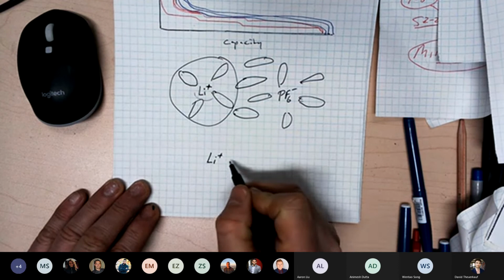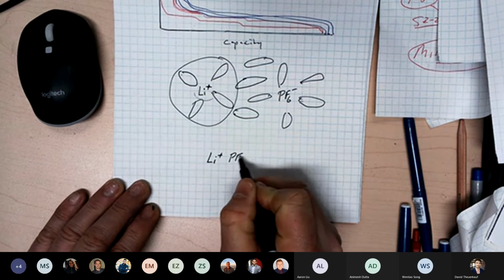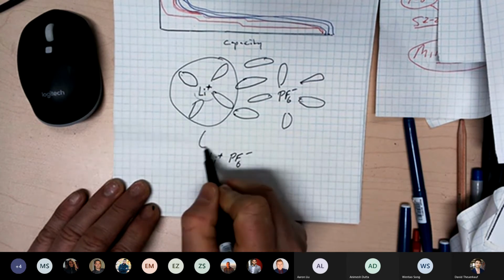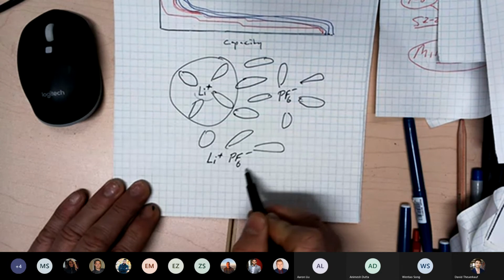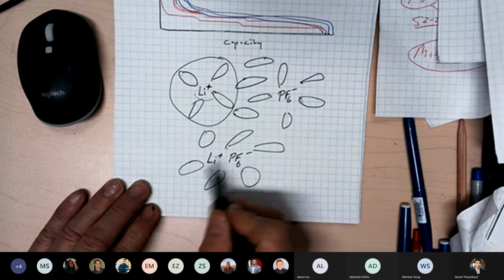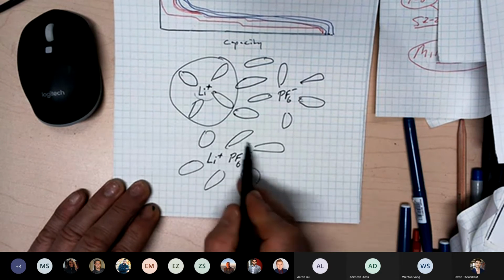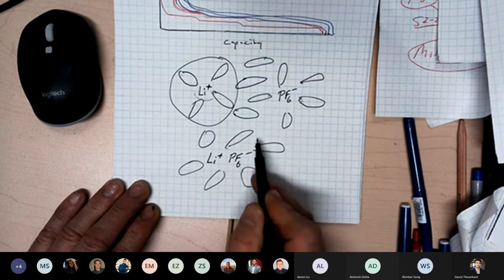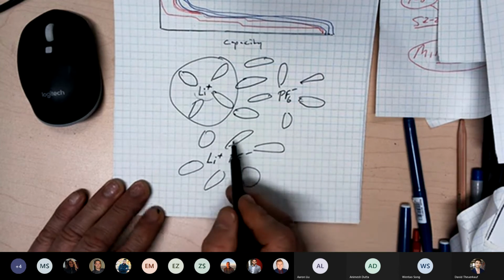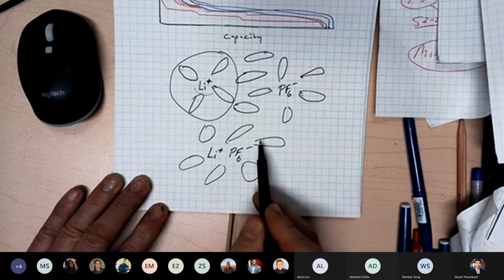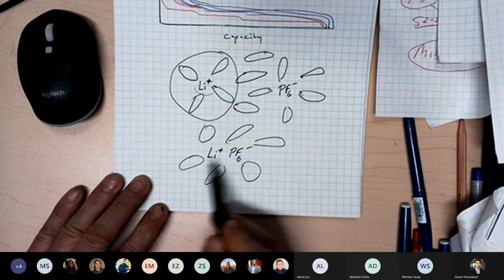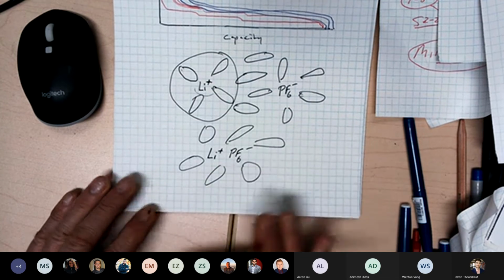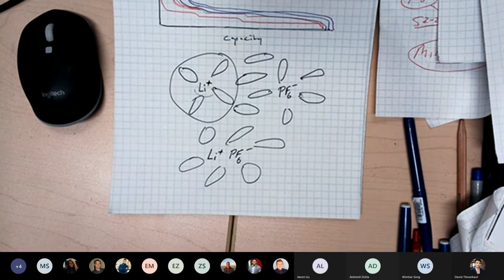But when the concentration gets large, you'll end up with situations where you've got the two ions in a sort of joint solvation shell, and that thing has zero net charge. So once the concentration gets big enough and you start having these ion pairs, they don't contribute to the conductivity. There's no net charge here. As this moves, it's not carrying charge in the solution anymore. So that's the impact of ion pairing.